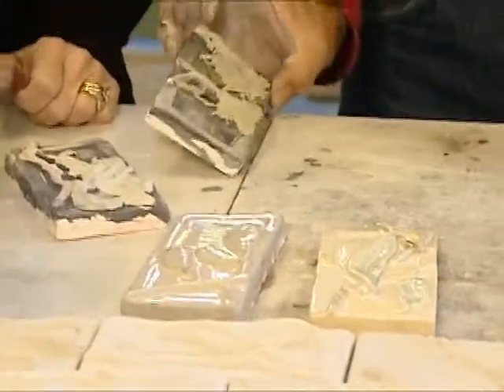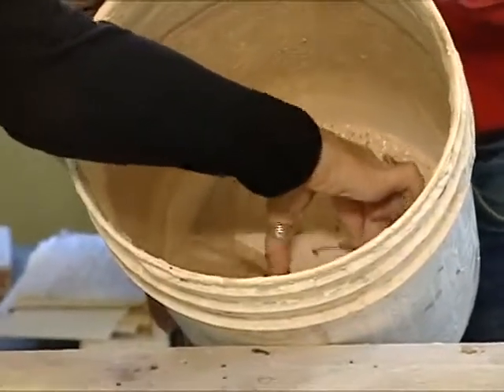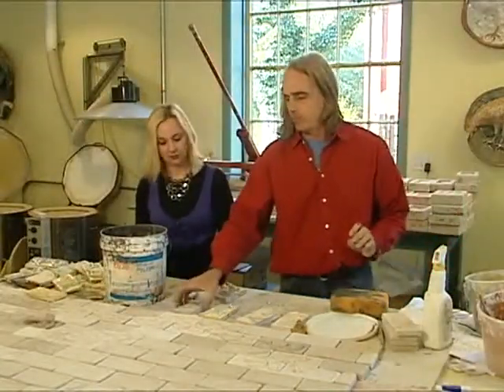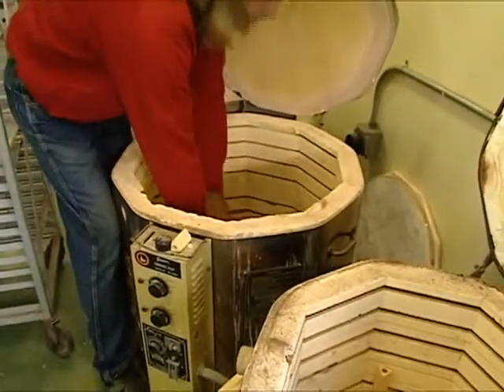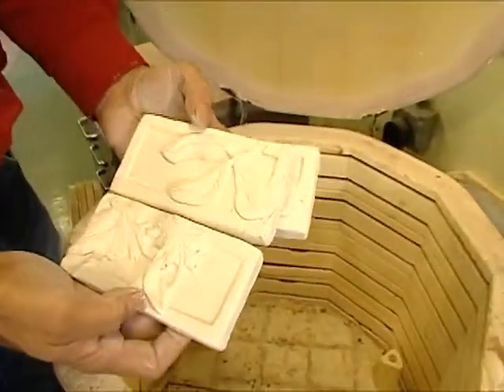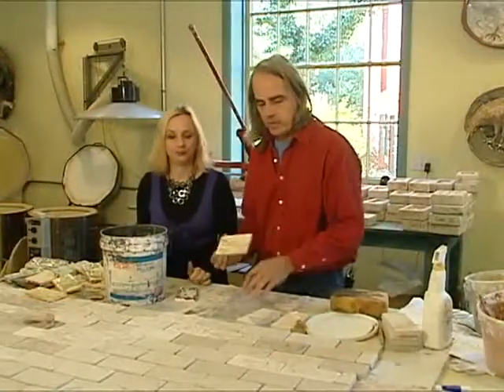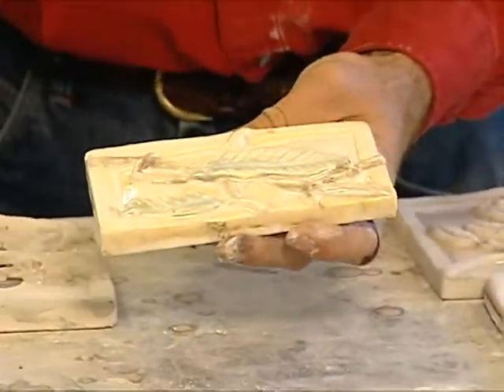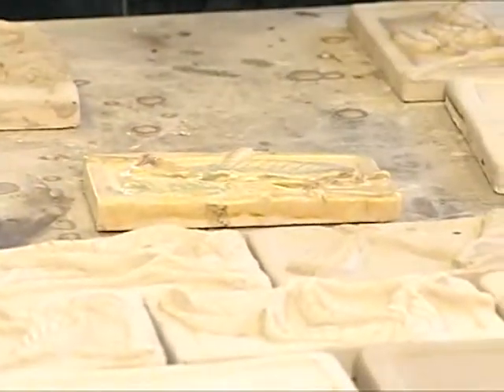The clay is very porous and it soaks up all the water. The chemicals are held in suspension with water, and the clay absorbs the water. When the tiles get glazed, we put them back in the kiln and make sure they don't touch. They again go to a little more than 1,900 degrees Fahrenheit — a really bright red heat. After about eight hours of firing and eight hours cooling down, we take them out. It's better that one person does all the glazing so you get the right amount wiped off each time for consistency.